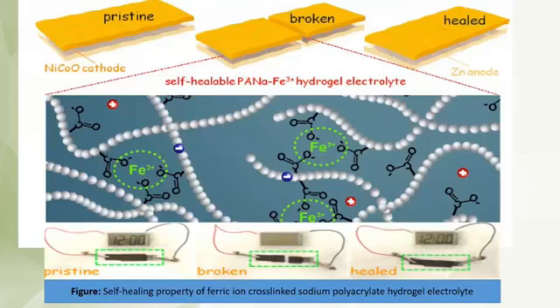So another beauty of the hydrogel electrolyte is, using what they call hydrogel, is due to their self-healable properties. Just say we take the pristine and we cut them into two pieces. If we join them again, then they can grow together due to the cross-linking, and they can show the performance they showed before they are broken. So this is what we call as the self-healability properties of the hydrogel.